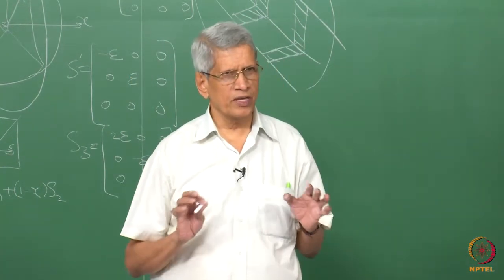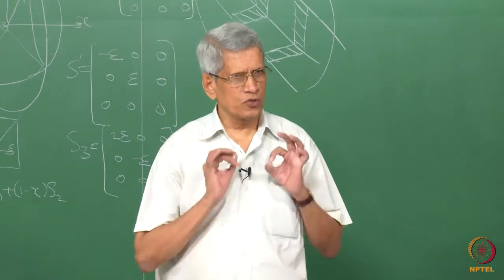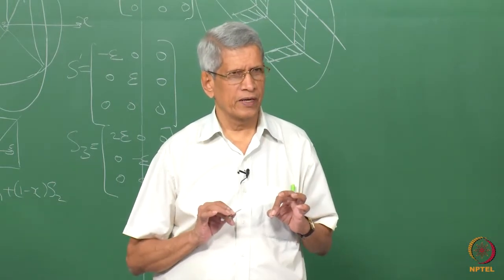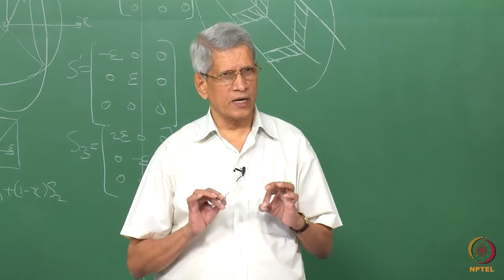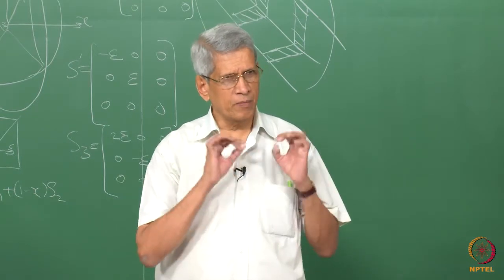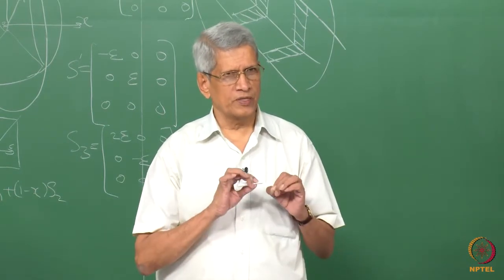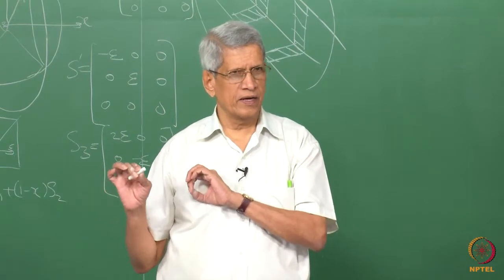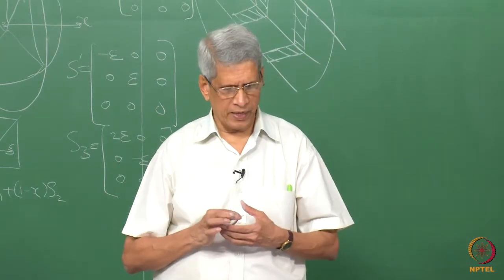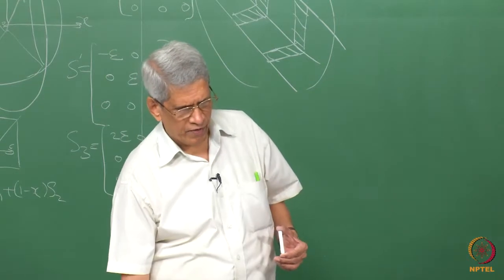understanding the crystallographic theory? First, choose a unit cell which contains the same number of atoms per unit cell as in the case of the transformed matrix. And that is what we have done.